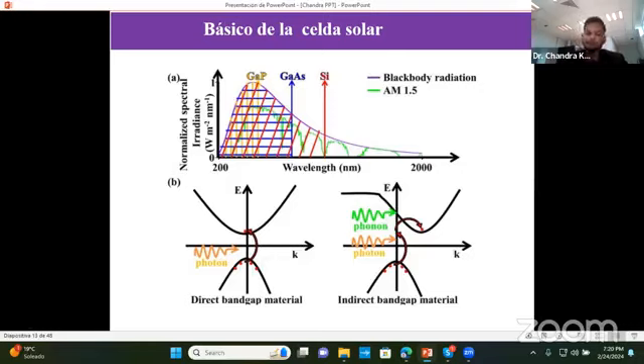the area. The question that always comes to mind when we establish a solar panel or solar cell is which light they might absorb. If we are talking about silicon, the band gap of silicon is around 1.12 electron volt. If we convert in terms of wavelength, that would be around 1000 to 1100 nanometer. What does it mean? It means a silicon-based solar cell might absorb light if it has a wavelength in the range of 1000 to 1100.